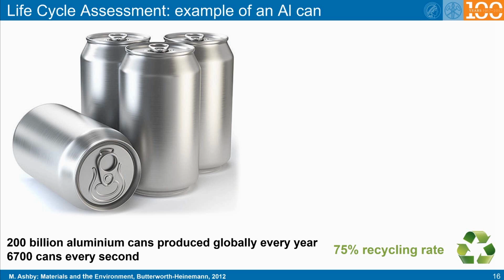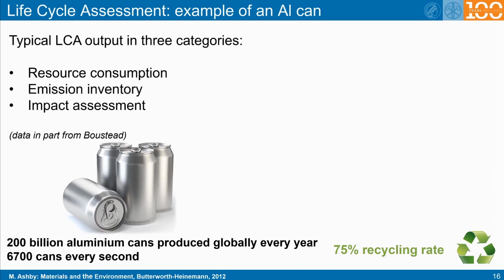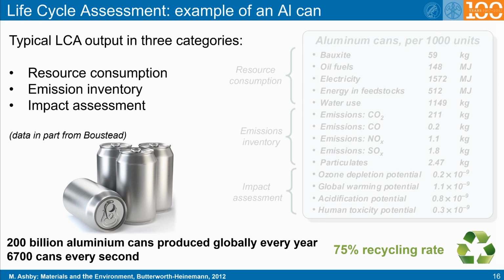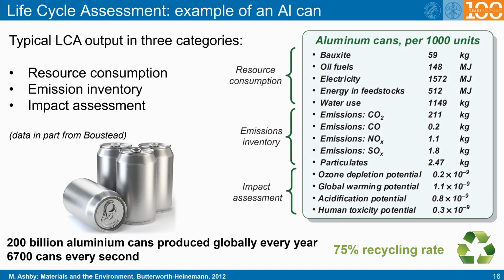In that context, the aluminium can is a nice example for a life cycle assessment. 200 billion aluminium cans are produced globally every year, which translates to 6,700 cans produced every second. For 1,000 cans, the life cycle assessment shows all the resources that have been consumed. It becomes apparent that particularly the huge consumption in electricity is a high burden. Actually, currently 2% of the world's energy use is spent on producing aluminium. This is due to the high enthalpy of formation of the aluminium oxide. Also, the consumption of water is rather high.